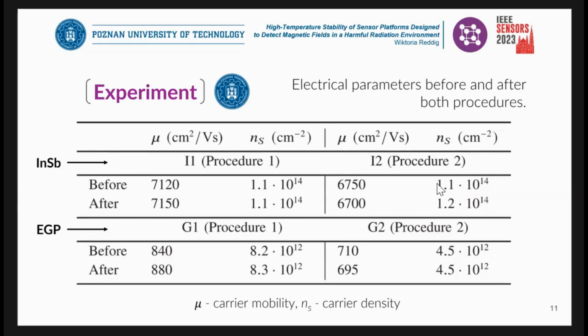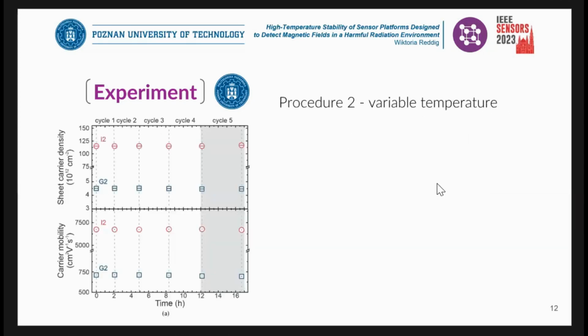Now let's dive into the second procedure results. Here you can see the carrier mobility and density results. The points indicate the room temperature measurements. With red circles, we mark the indium antimonide sensors, and with the blue squares, graphene. As you can visually see, during this whole process, they were all very stable, and the procedure did not do any permanent damage to the sensors.